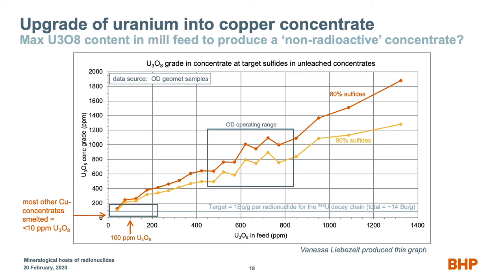Now, a slightly complicated graph, but it did show us a lot. From all of our geomet samples, thousands of them, we can look at the uranium feed in the sample, and look at the uranium concentration in the concentrate once we do a float on that sample. And it's simple: we can look at 80% sulfides, and at high-grade uranium, you have high-grade in the concentrate. And as that head grade goes down, so does the uranium that recovers there.